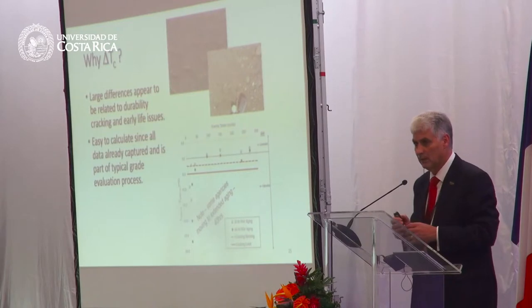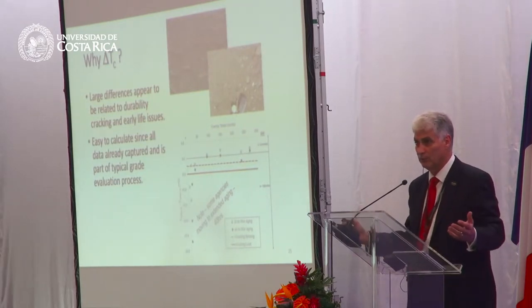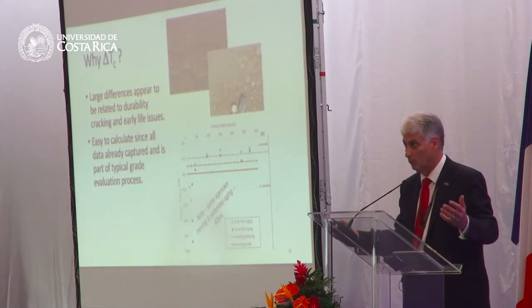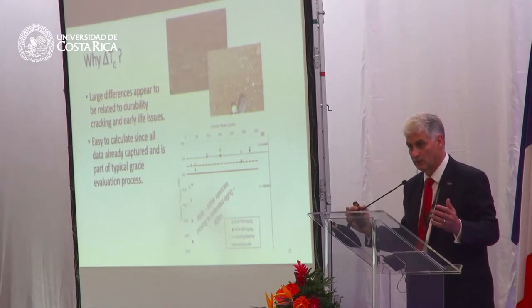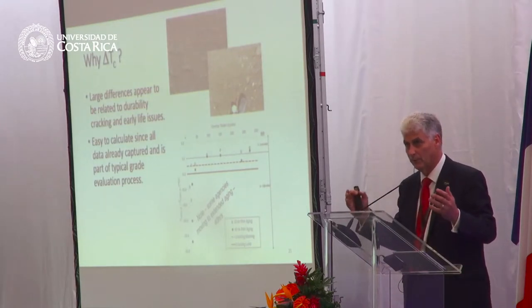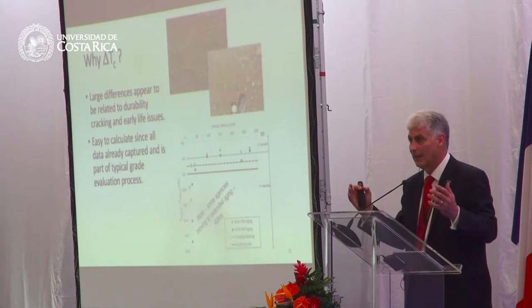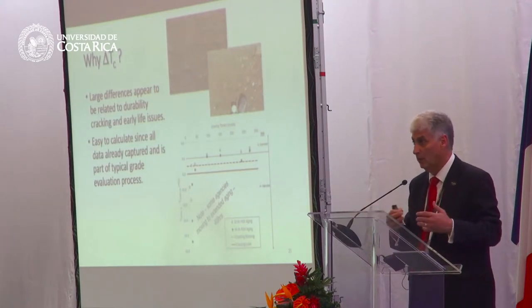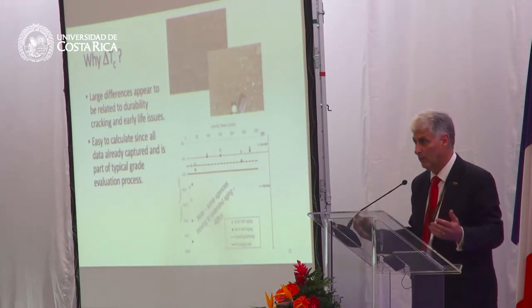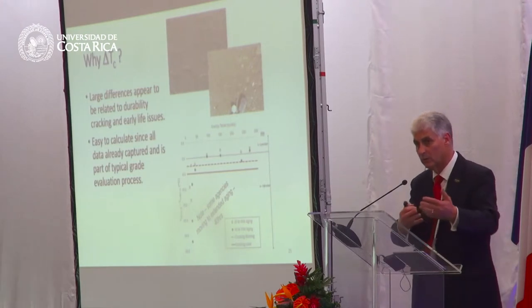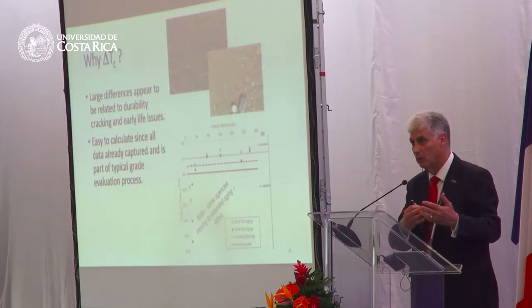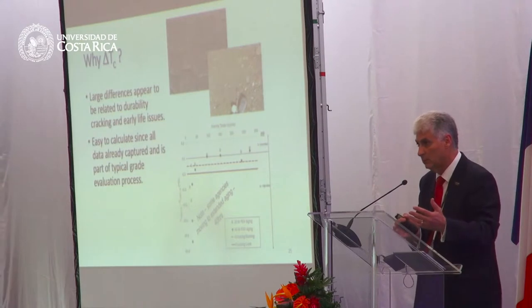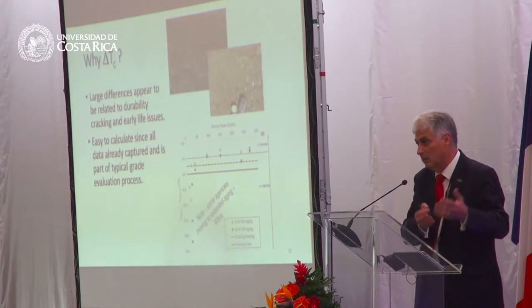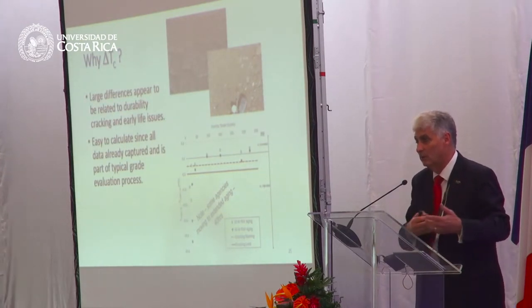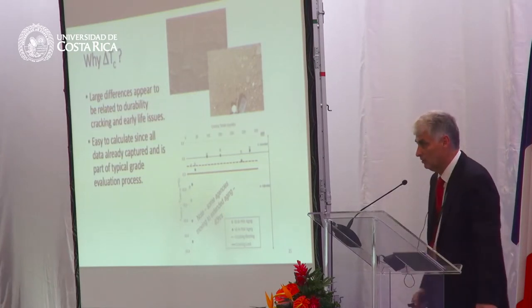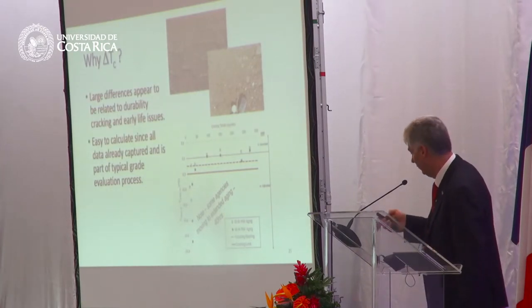Some folks feel that, well, I don't have real cold temperatures, why do I need to use a bending beam rheometer? But what the bending beam rheometer does is give you a characterization of the stiffness of the binder in the high stiffness region. And regardless of your climatic zone, your binders will still oxidize to that high stiffness region. So the characterization of the stiffness, even though you might not have minus 20 or minus 10 degrees temperatures here, is still valid because you're measuring the stiffness of the material in that region.